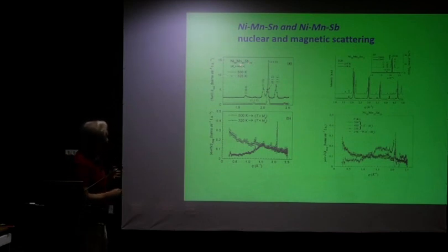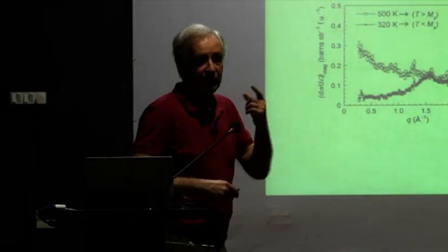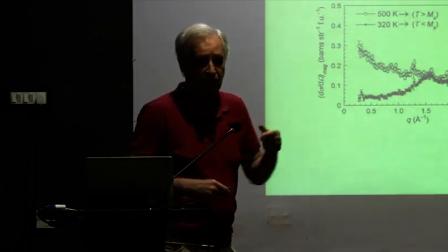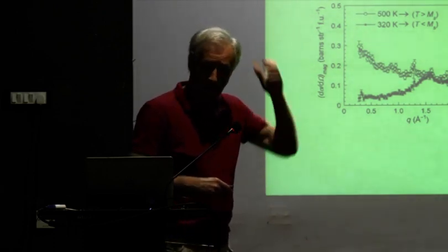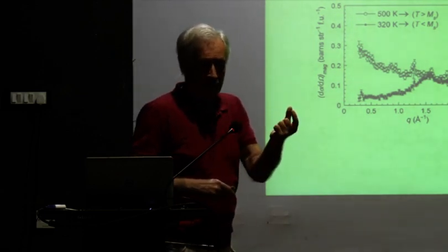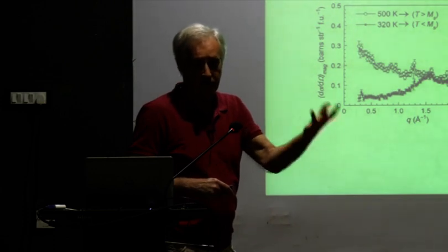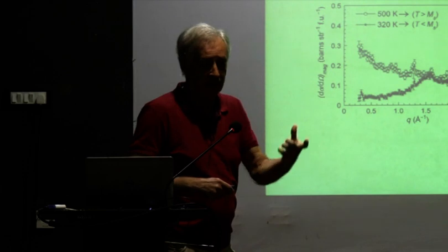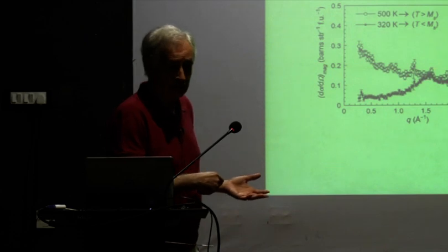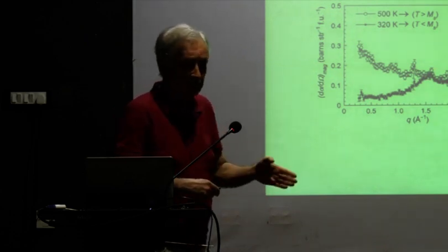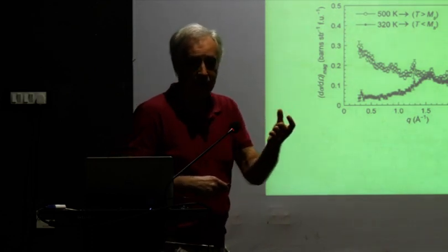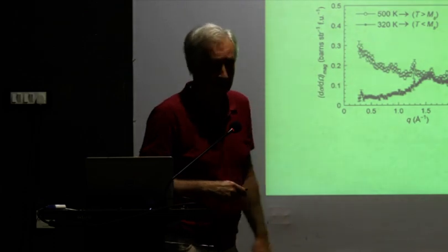These are off-stoichiometric systems. There's a lot of manganese in here, so you have lots of manganese nearest neighbors and manganese next nearest neighbors. That will become more evident in the talks that I give tomorrow and the day after tomorrow concerning INVAR. The nearer neighbor interactions in manganese are antiferromagnetic. The further apart manganese atoms act ferromagnetically, and here you see both. It's just that below the martensitic transition, it appears that the distances have exceeded a certain critical distance, and there's no ferromagnetism. Everything's gone down.